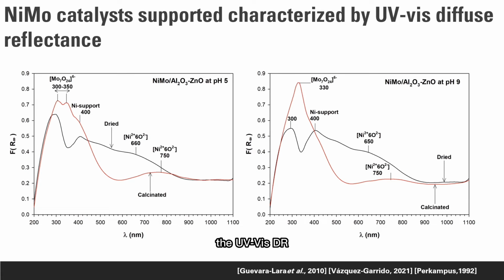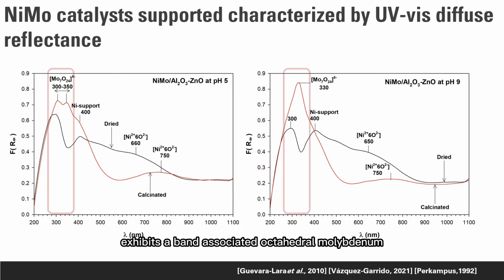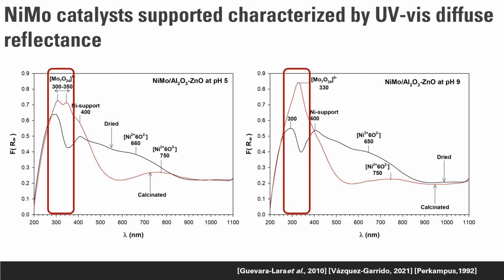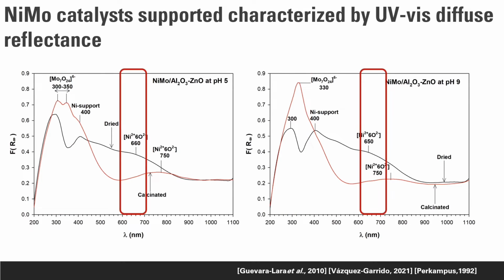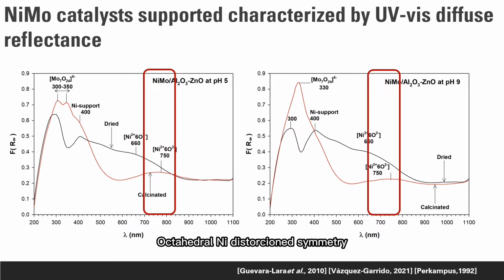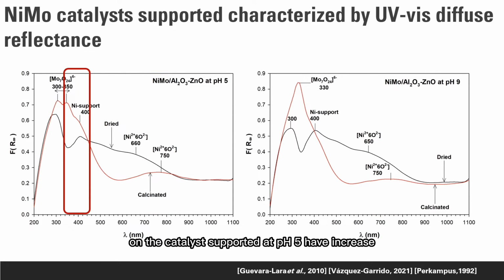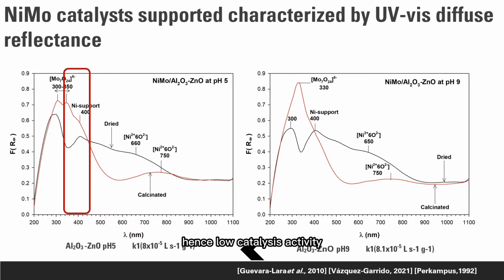The UV-Vis-DR spectra of nickel molybdenum alumina zinc oxide exhibit bands associated with octahedral molybdenum. It shows nickel with octahedral symmetry, and when the catalyst is calcined, it shows nickel with distorted octahedral symmetry. The catalyst supported at pH 5 has increased nickel-alumina or nickel-zinc oxide interaction, hence low catalyst activity.